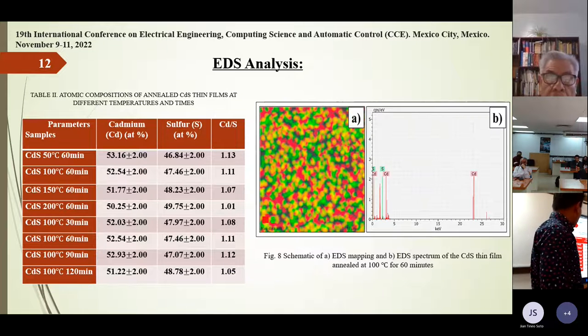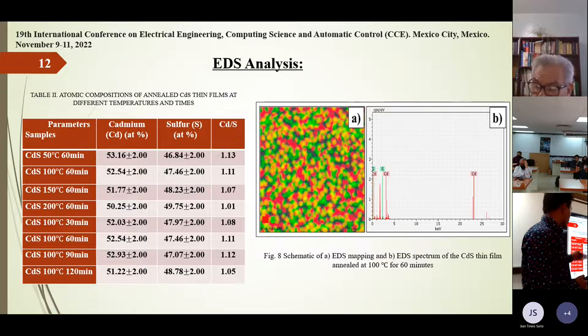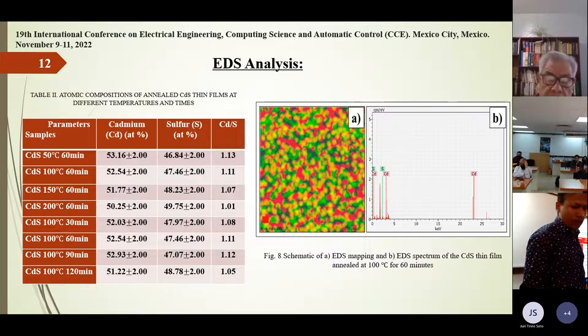From the EDS analysis, we have observed some variation in the compositions. As mentioned earlier, before annealing it was 55 cadmium and 45 sulfur. After increasing the temperature from 50 to 200, you can see that it is changing toward a symmetrical composition of the samples. Even with increasing time, it is also becoming a symmetrical composition. This pattern can be found after annealing, and the figure shows the mapping and the spectra of the